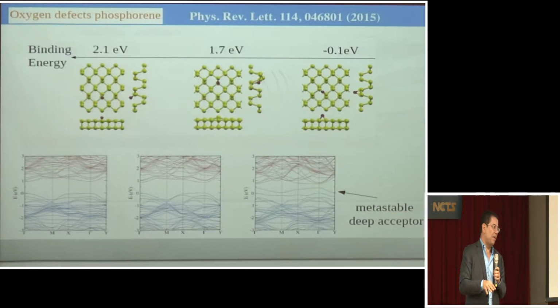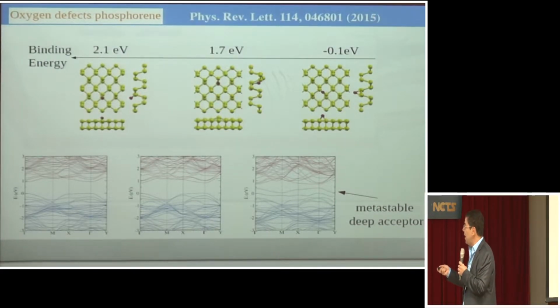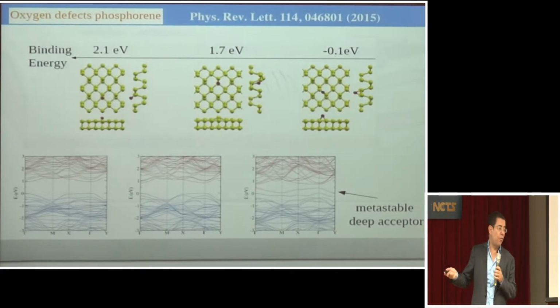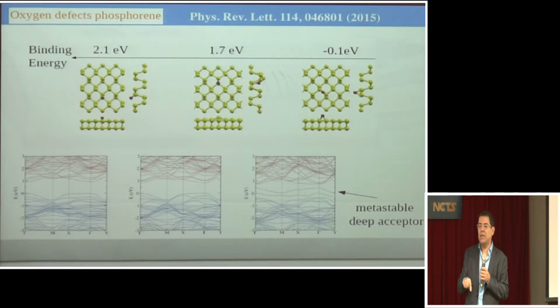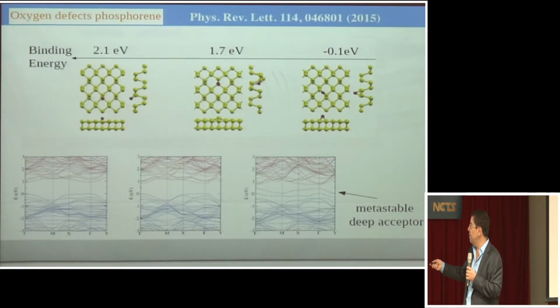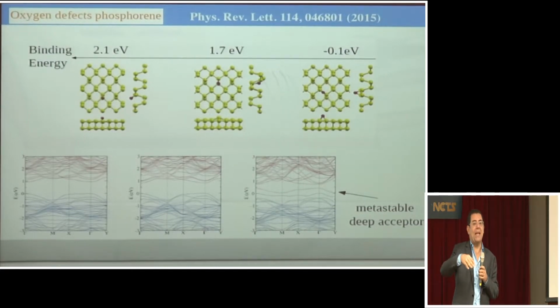But the nice thing about these materials is that we can find ways to reduce or eliminate oxidation, in a way that they become very useful for applications. So this is an example of studies of what happens if you have oxygen in the crystal structure of phosphorene at different positions. This is another thing, because the crystal has low symmetry, the oxygen can enter in many different positions in the structure. It can make bridges, like an epoxy type binding, or it can be just connected to an atom. And what happens is that this has a direct consequence in the band structure, obviously, because once the oxygen is there, in a semiconductor, you're going to generate what's called mid-gap states, which are impurity states that exist either in the center of the gap or close to the band edges.